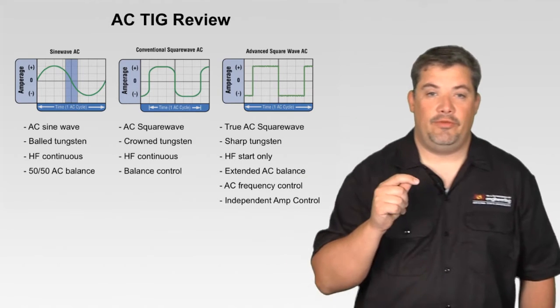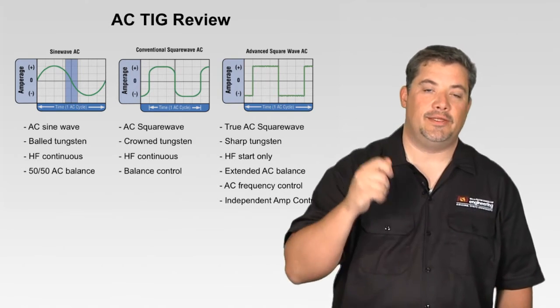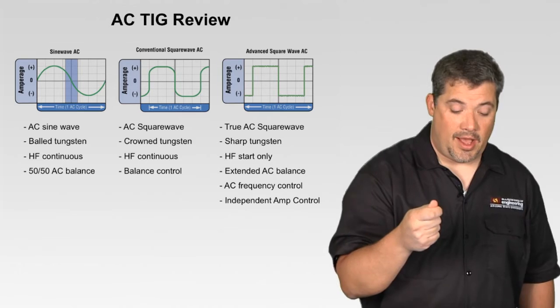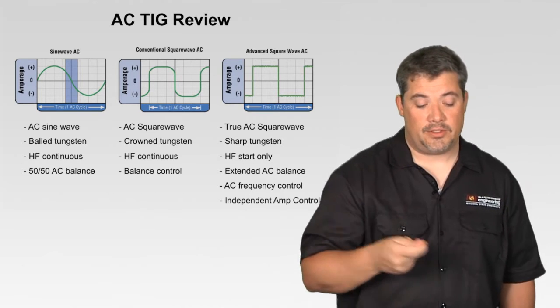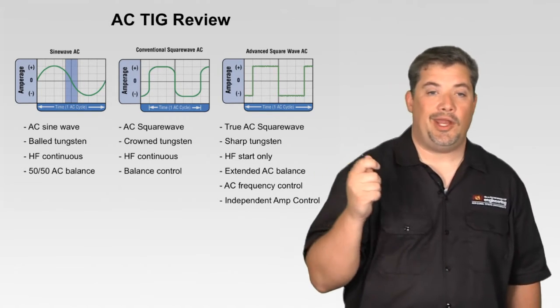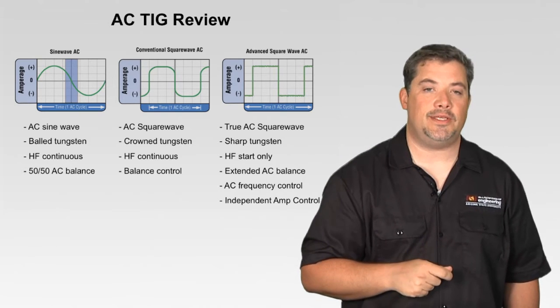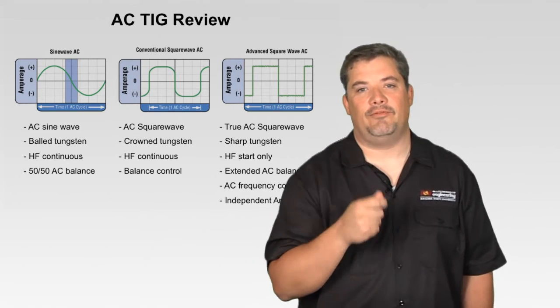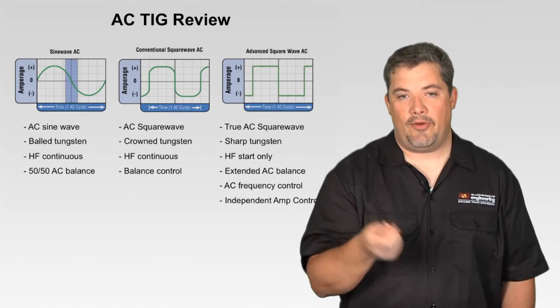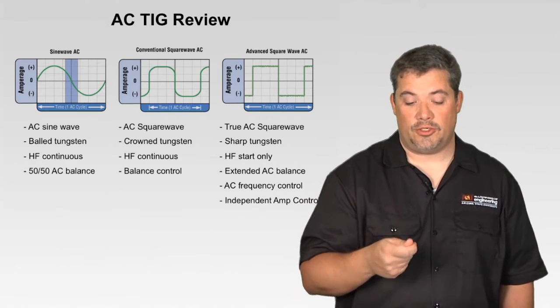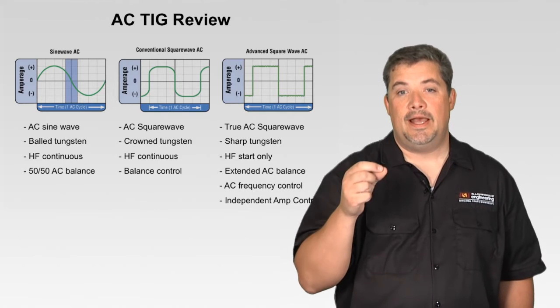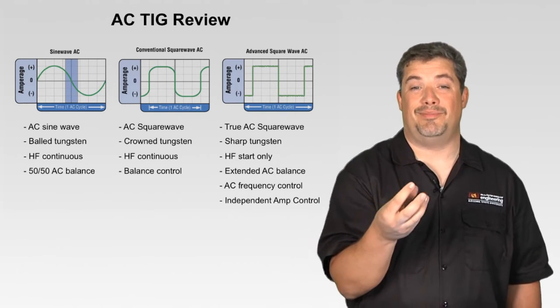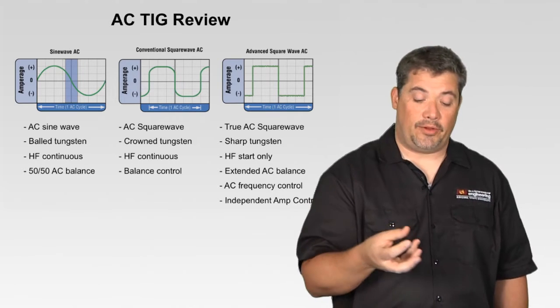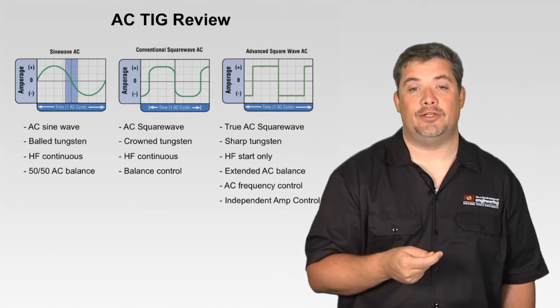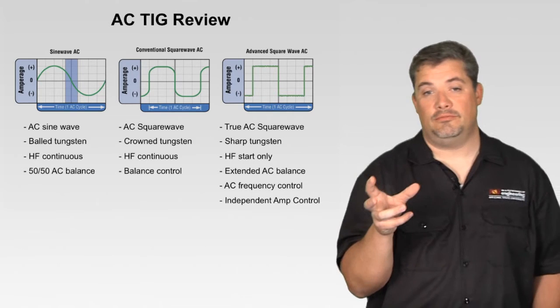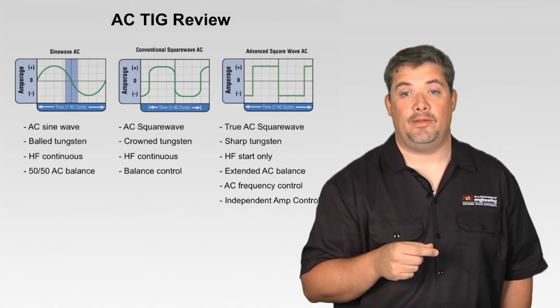So, AC TIG review. From the old school sine wave ACs that really don't exist anymore, you had a sine wave, you had a ball on your tungsten, you used high frequency all the time, and you had no balance control. It was 50-50 AC. Then in 1976, that conventional square wave AC came. Now it gave me that more square shape, utilizing the energy more efficiently. I used a crowned tungsten, so it doesn't make as big of a ball. I use high frequency continuously still, but now I had balance control, and that balance control was limited, but it was certainly better than 50-50.